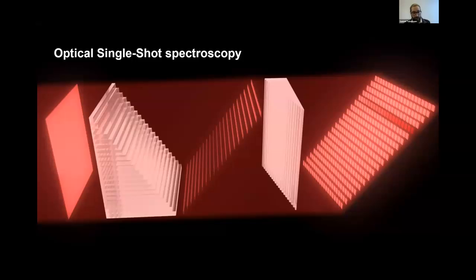And for this, we turn to single shot spectroscopy. So with conventional pump probe, we're unable to see what's going on within the photo switching because once the material is photo switched, it's permanently in the magnetic phase and you need to wait to warm it up to take it back to the insulating phase. You can't do that with a second ultra short laser pulse. You'll just end up making more metallic phase until the system saturates. So what we use is single shot spectroscopy.